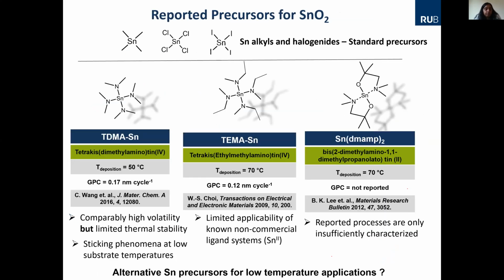So I will briefly summarize this slide. There are several precursors. You can have the alkyls, the chlorides, or the iodides, but most of them have certain drawbacks. The only commercially available precursor is tin amide here with the nitrogen coordination. The others are research-oriented publications where it's not commercially available. The most important precursor is the amide, and they have high volatility but limited thermal stability, and that's not good for ALD. The non-commercially available precursors may not be optimal, but people have tried, and that's the goal of the researchers, to look for new molecules, new processes.